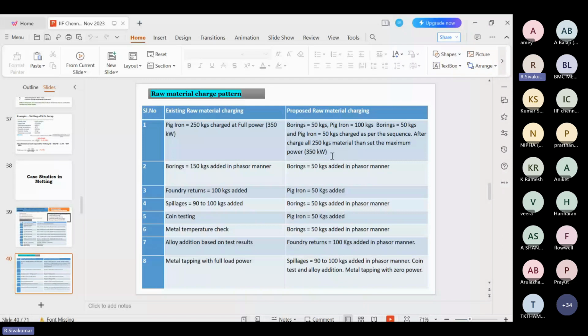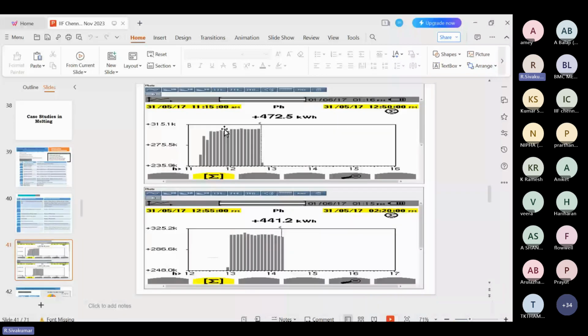Here the 250 kgs of pig iron is added. Next, borings are added sequentially in a slower manner. Borings 50 kg, pig iron 50 kg, again boring. So in this method, the existing energy consumption is 472.5 kWh per melting campaign. Here we are achieving only 441.2 at the rate of 550 to 580 kgs of liquid metal. For this 472 and 441, the metal output is almost 550 kgs, because the crucible capacity is 500 kg and the furnace power capacity is 350 kilowatt. It's a medium small foundry industry.